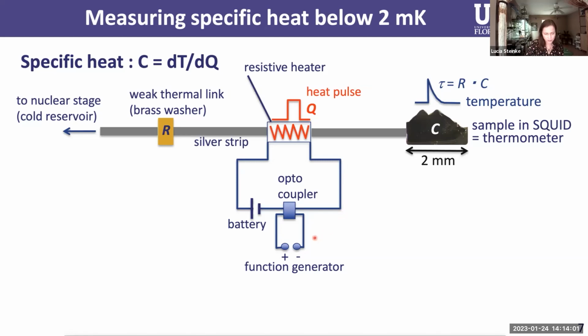The solution to that was to electrically completely decouple the circuit for the function generator from the circuit providing the heater power via light, via using an optocoupler. And now it's a battery that's heating the sample. That trick allowed us to actually get the sample cold. Now, the second challenge was how to measure its temperature, because there aren't really that many good thermometers that work under these conditions at super low temperatures for such a tiny sample. See, this is only 2 millimeters.